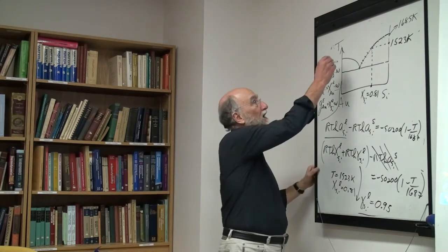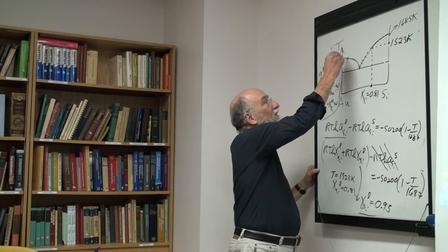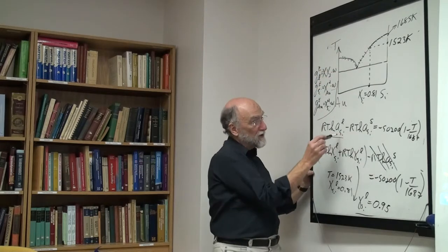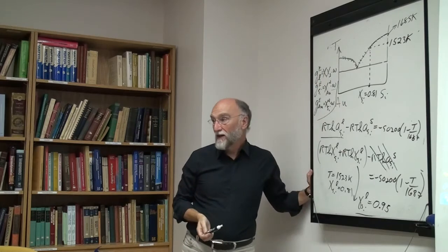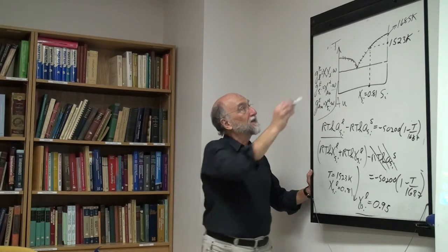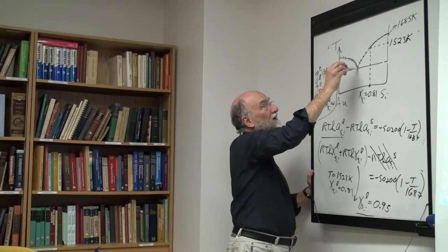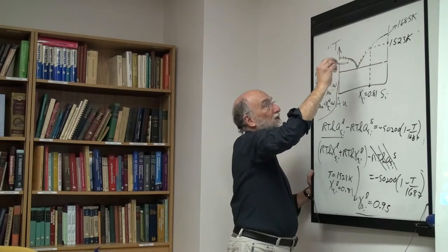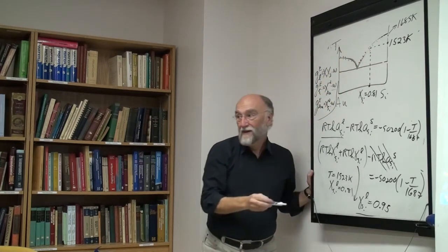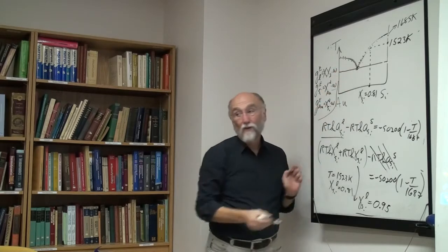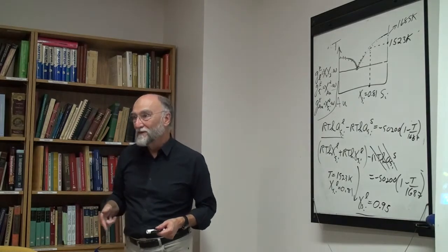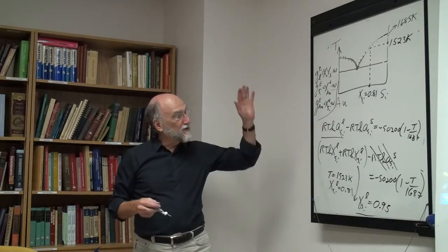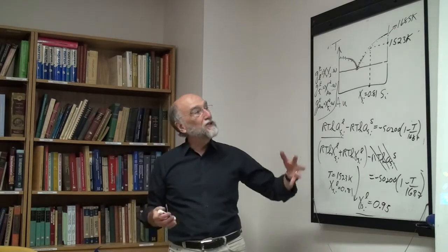Now the GXS on this liquidus is the same thing. All along this liquidus I use the other equation with gold, and I'll get the excess Gibbs energy of gold along that line. So I get the excess Gibbs energy of gold from here to here, and I get the excess Gibbs energy of silicon from here to here. I have one point at which I'm going to have both. And I can use that as the endpoint of my Gibbs-Duhem integration, and I'll talk about that next week. This is just to lead up to it, to show you what information you're getting.